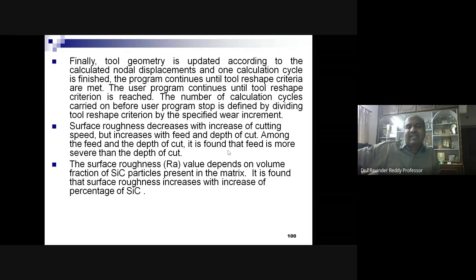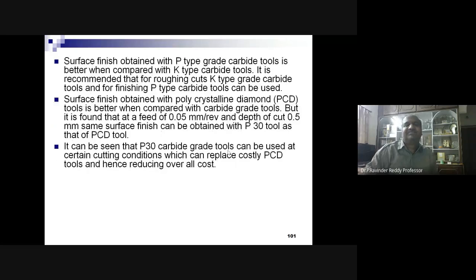It is found that surface roughness increases with increase of percentage of silicon carbide. Surface finish obtained with the P-type grade carbide tools is better when compared with K-type carbide tools. It is recommended that for roughing cuts, K-type grade tools, and for finishing, P-type carbide tools can be adopted.